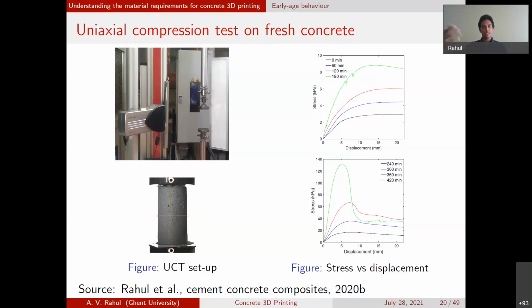So if you need to characterize stress, you need to use an updated cross-sectional area to convert force to stress. Because of the large lateral deformation, if you use the original cross-sectional area, you will not get a realistic estimate of the stress value. So here we see stress versus displacement values obtained at different time intervals, 0 minutes, 60 minutes, 180 minutes. So the maximum value obtained here can be used to obtain the compressive strength at different time intervals. Then plotting that with respect to time gives the evolution of the compressive strength.